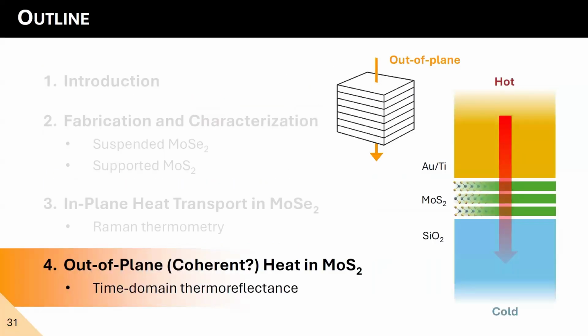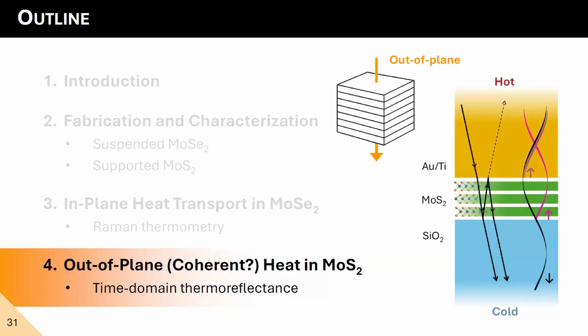So let's move on to the last and biggest section of my talk. Here we want to study the out-of-plane heat transport in molybdenum disulfide by using time-domain thermoreflectance. So as we've said, we will use plates supported on a substrate, which is our heat sink, and we will use a metal transducer, which is what will give us our observable. The change in reflectivity of this metal will tell us how much the temperature has increased at the surface, and therefore we can relate it with the thermal properties of our material. Importantly, we studied the possibility of coherent heat transport in a single TMD, which has never been done before.